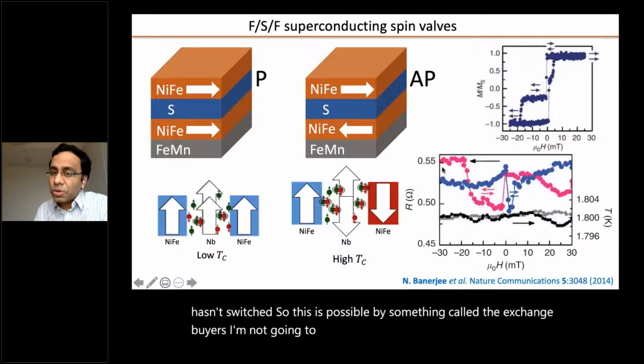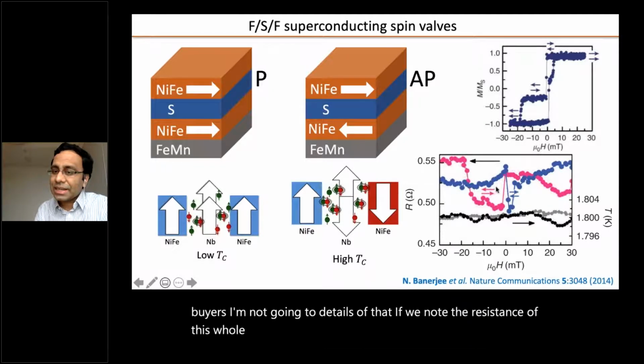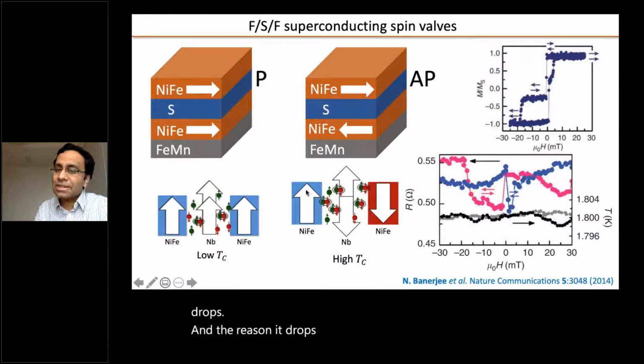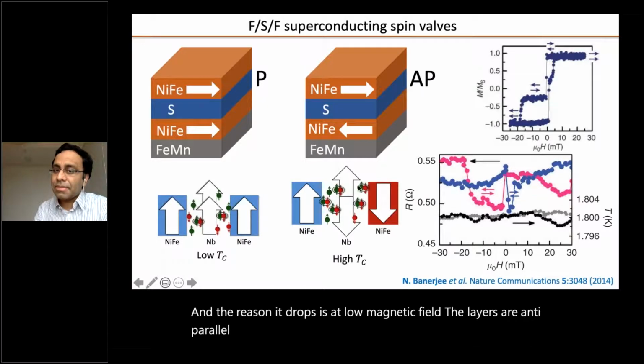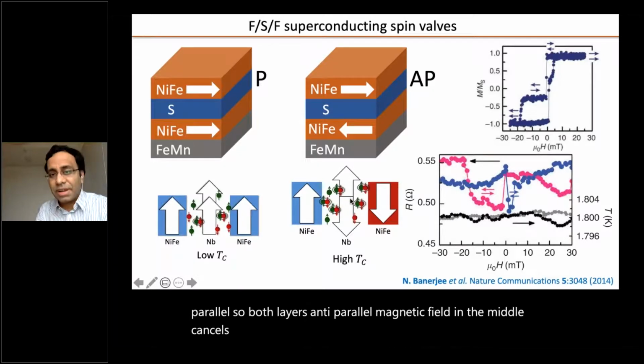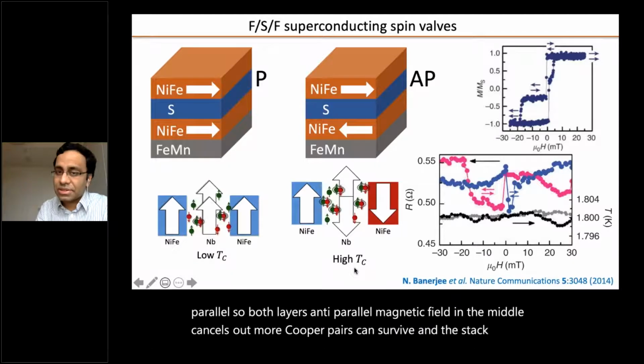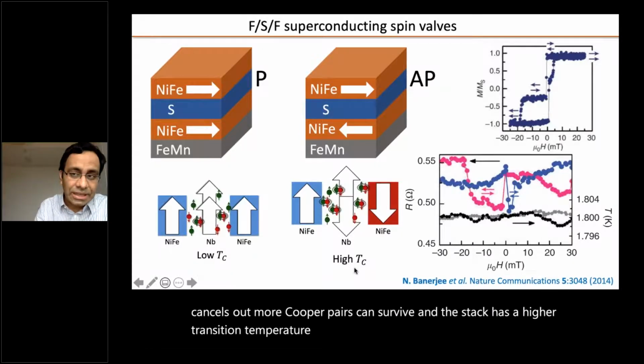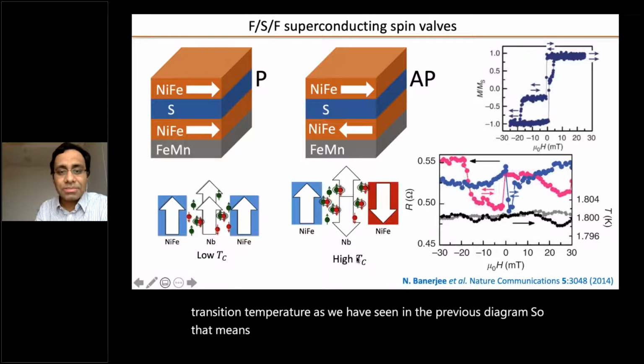If we note the resistance of this whole stack, you will see that at low magnetic fields, the resistance drops. And the reason it drops is that at low magnetic field, both the layers are anti-parallel. The magnetic field in the middle cancels out, more Cooper pairs can survive, and the stack has a higher transition temperature, as we have seen in the previous diagram. So that means the resistance is lower.